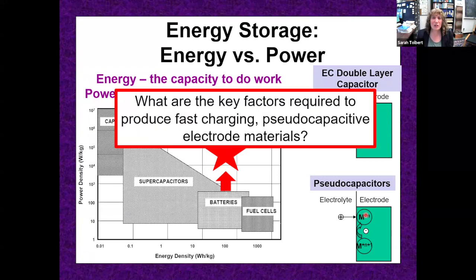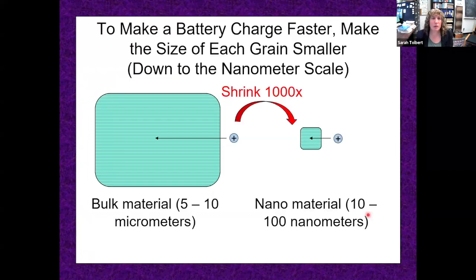And what we'd like to ask is, what are the key factors required to produce fast charging pseudocapacitive electrode materials? Okay, well, the simplest solution is just to make the material smaller. If it takes too long to move a lithium ion across the 10 micron size, the bulk material that's used in most batteries, convert that material to a few tens to hundreds of nanometers in size, and now the lithium doesn't need to move as far.